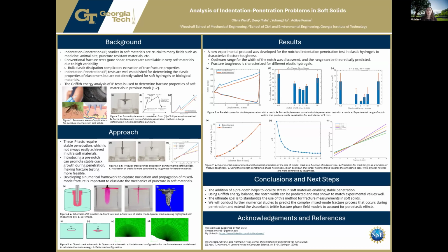Indentation penetration, or IP testing, is an alternative approach that has been used for elastomers. This test is local and provides a more accurate prediction for the fracture toughness because there's no need to account for viscoelastic dissipation in the material. However, it does not directly translate well to ultra-soft materials where unstable crack growth and inconsistent results are common. An example of this can be seen in Figure 2, where there's a very large deformation in the hydrogel before fracture. So the key question we want to address with this work is how can we modify indentation penetration tests to reliably measure fracture properties in soft solids?